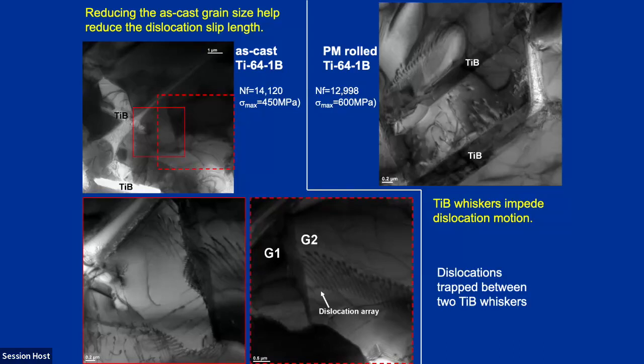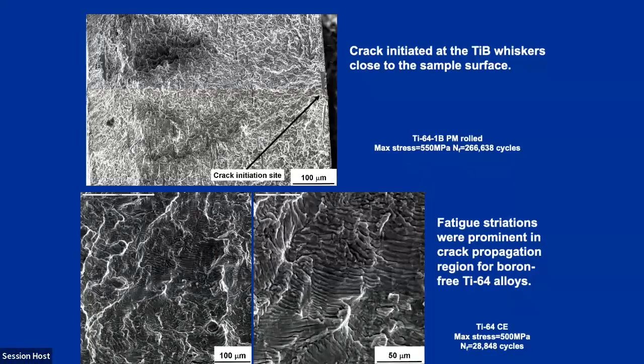And reducing the as-cast grain size can help reduce the dislocation slip length, reducing the stress concentrations, reducing the ability to crack. That's a good thing in terms of fatigue or tension. And I'm glad that Thomas Klein showed some fracture surfaces in fatigue earlier. We have very similar features, whether you add boron or don't add boron in Ti-6-4, compared to his wire AM materials. And so the cracks, as we saw in tension, typically initiated at whiskers, and they were typically close to the fracture surface, but we still could get ductile type of failure away from the crack initiation site.